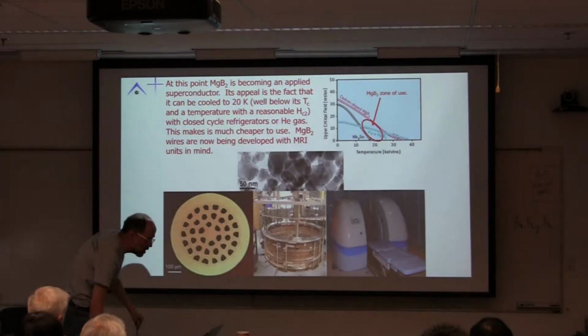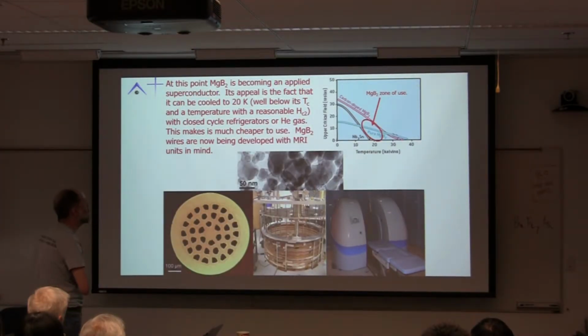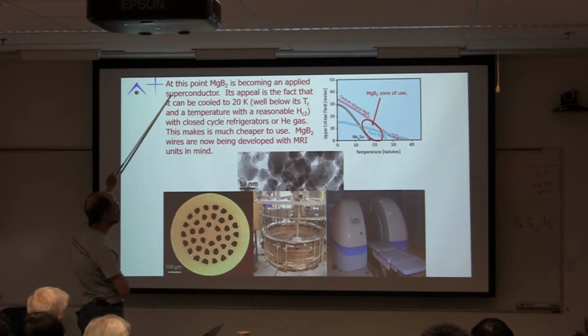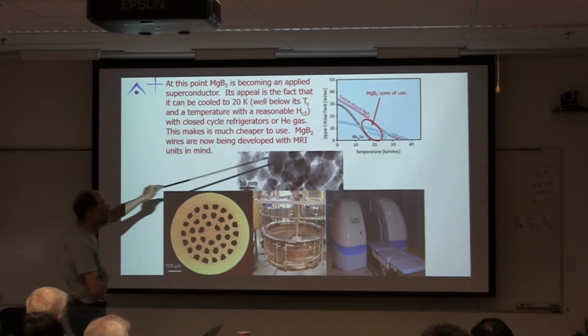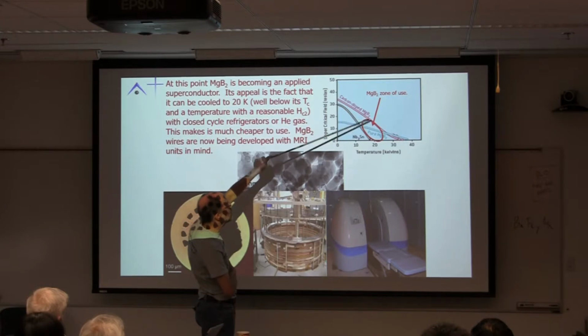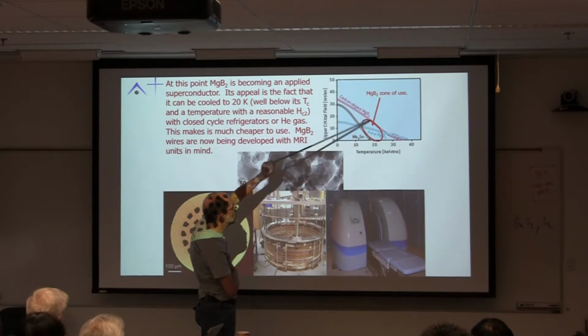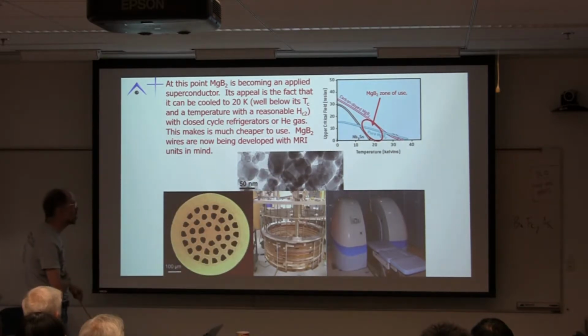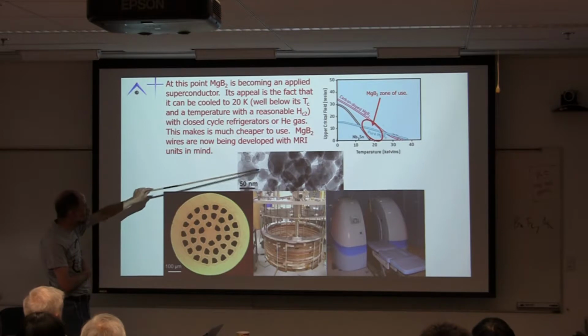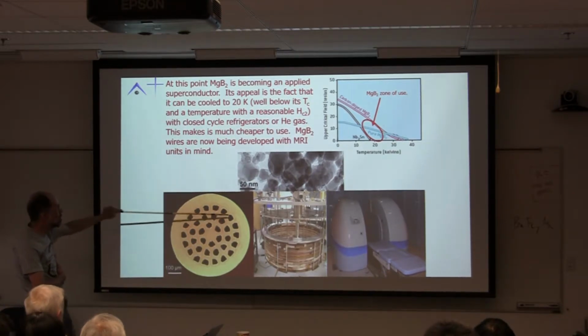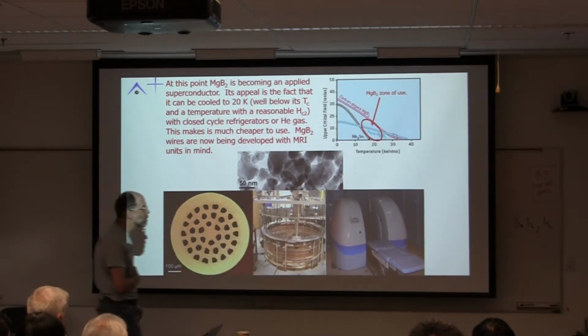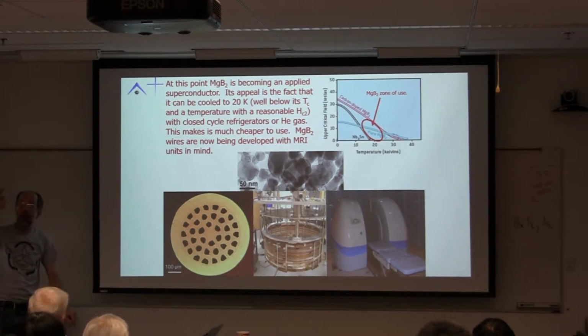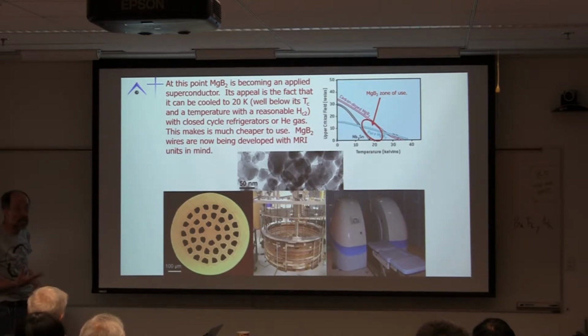And at this point, humanity, not my own group, but humanity as a whole, has taken MgB2 and has turned it into a practical superconductor. You now have what's called the MgB2 zone of use, because here, niobium-3 tin doesn't even superconduct, and MgB2 is superconducting and has a relatively respectable Hc2. You can make nice powders, you can do powder-in-tube multi-filament, you can wind them in coils, and you have prototypical Helmholtz geometry MRIs that you can cool at 20 Kelvin that are lighter and cheaper to use. Okay? So MgB2 is actually finding a niche in industry, about 15 years after.